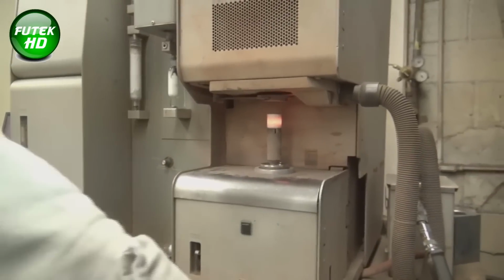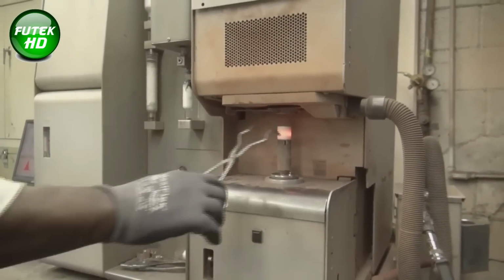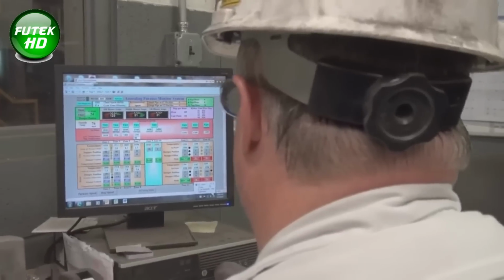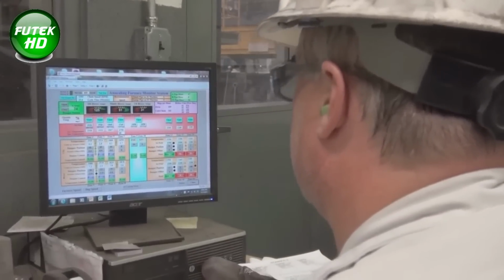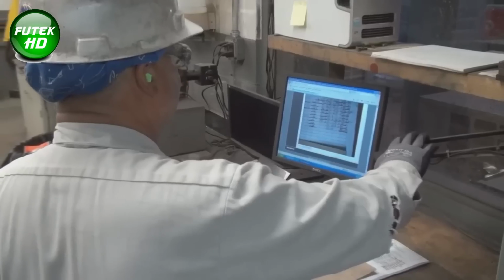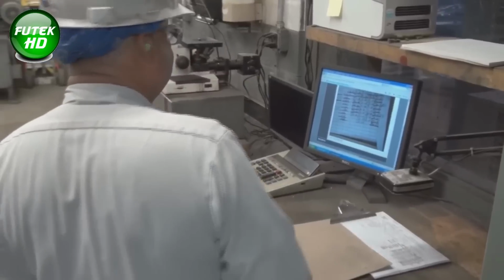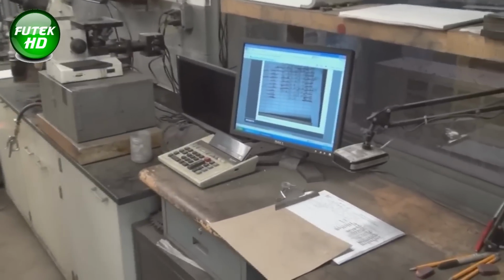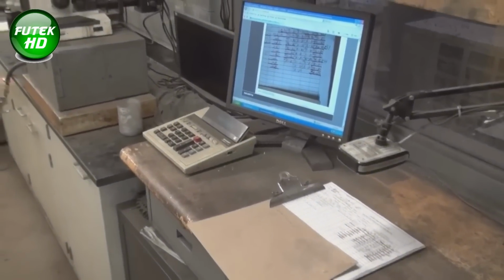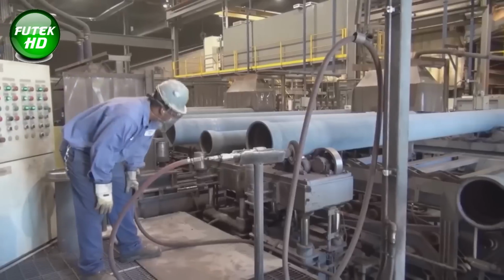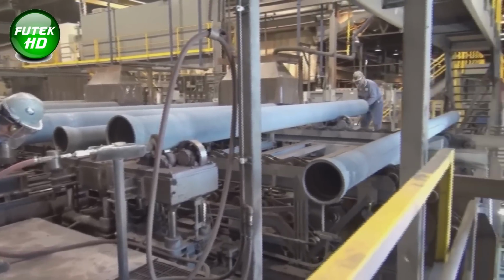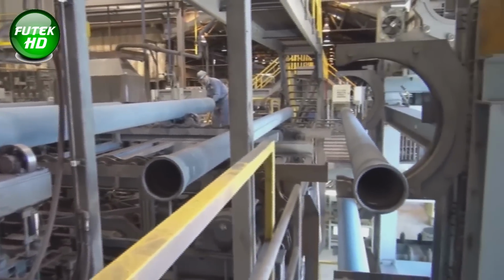Samples are taken from the cupola, after desulfurization and after magnesium treatment. These samples are sent to a melting lab for analysis using advanced equipment like spectrometers and infrared analyzers, which detect around 20 elements. Strict calibration standards are followed to ensure accuracy. This real-time analysis allows operators to make adjustments as needed to maintain the correct composition.